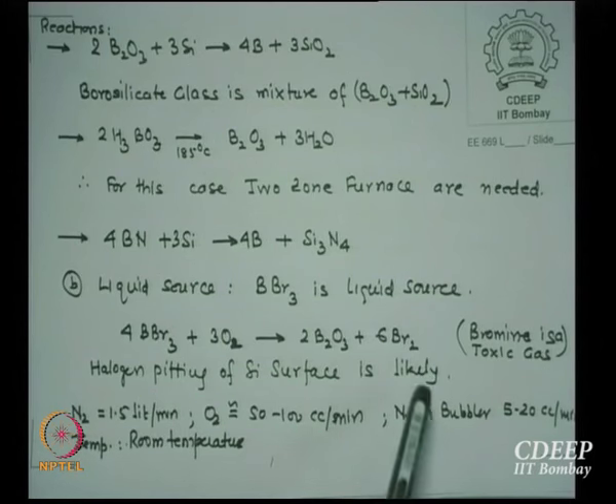Now this is a problem. Bromine is highly toxic, as well as being highly reactive to silicon, so it gives what is called halogen pitting. When we were making 5 micron devices or 3 micron junction depth, that pitting was irrelevant. But with 100 nanometer junctions, the pitting may be 100 nanometers. So there are issues now which in 25-30 years we never bothered about. Now no one uses BBr3. Earlier almost everyone used BBr3. So this is the progression. Now mostly people will not even use either of them.